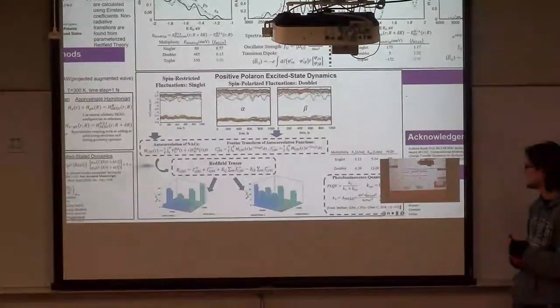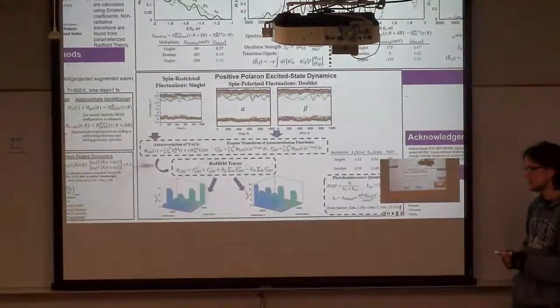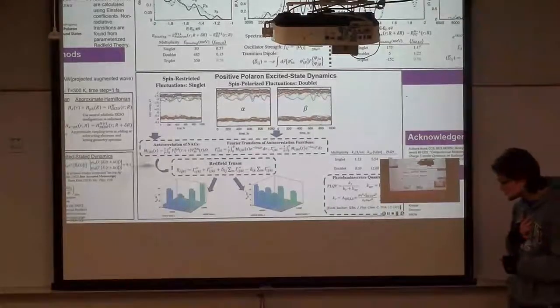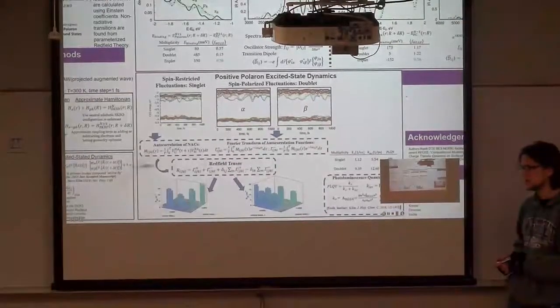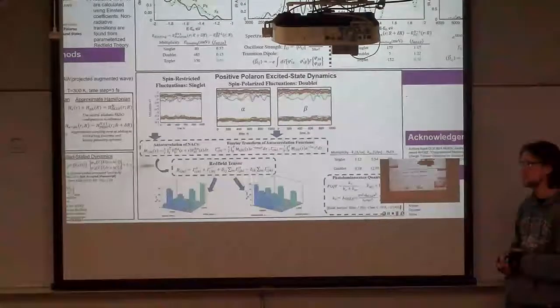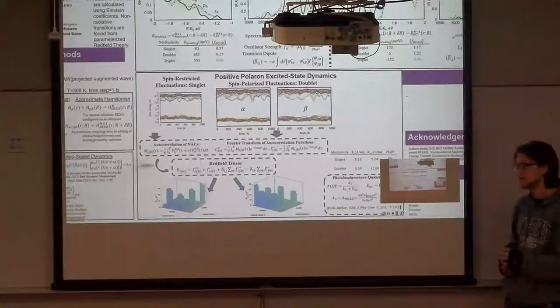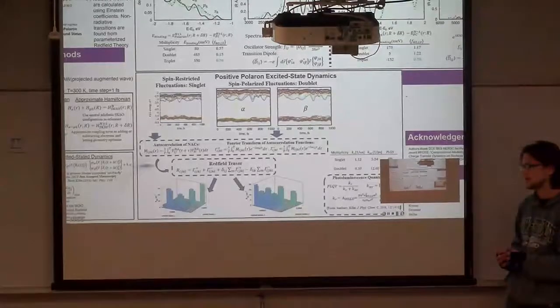Of course, ideally one would rerun all couplings at lower temperature, but can you just scale it down and say it will be linear or according to some other function like the Bose-Einstein distribution, so the rate will be smaller, and then the quantum yield will change and become slightly bigger? If it is already 10 to the minus 6, it will never flash like crazy, but it will be a little more efficient at lower temperatures.